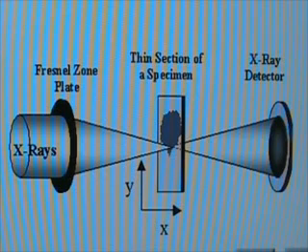So now we are running an experiment. We have put the sample inside the STXM and we are doing an analysis of one isolated carbon nanotube. But how is it possible to analyze something as small as one carbon nanotube using STXM? In fact, this instrument is able to focus X-rays coming from the synchrotron onto a very small spot on the sample, and the size of this spot is around 30 square nanometers. This is enough resolution to see one isolated multi-wall carbon nanotube.